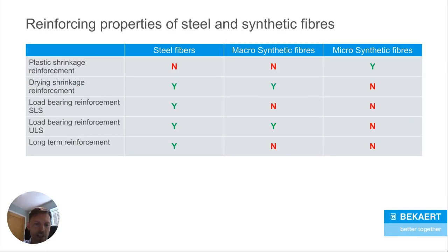So as a summary, we can see what different fibres can actually do inside concrete. So microsynthetic fibres can do something that steel cannot: aid against early age plastic shrinkage cracking. Very important on external concrete. If you're laying external concrete that doesn't have polypropylene fibres in there, you may get unwanted early age plastic shrinkage cracking. But after that, they don't add any strength to the concrete. So you can use steel fibres to reinforce your concrete due to the loads, or because of your serviceability limit state design. But polypropylene fibres cannot do the same. Macrosynthetic fibres could be used in the ultimate limit state design, but they will add substantially less ductility than steel fibre reinforcement.